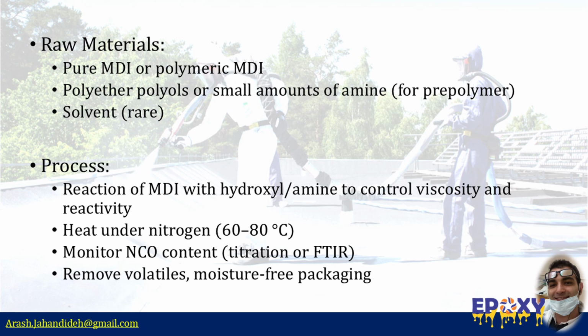The A side of a polyurea system primarily consists of isocyanate prepolymers, most commonly based on pure or polymeric MDI, that's methylene diphenyl diisocyanate. To fine-tune viscosity and reactivity, MDI is reacted with small amounts of polyether polyols or even amine compounds, forming a prepolymer or quasi-prepolymer. The manufacturing process typically involves controlled heating under a nitrogen atmosphere, usually between 60 and 80 degrees Celsius, to prevent oxidation and moisture intrusion. The reaction between the isocyanate groups and hydroxyl groups or amine groups must be carefully monitored to achieve the desired NCO content, which directly influences reactivity and shelf life. This is usually measured by titration or FTIR spectroscopy.